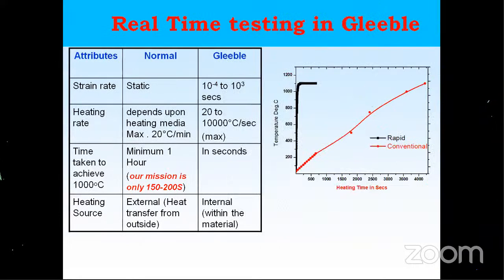Then, this is very, very important. This is, in fact, my own finding, or my own idea actually. Normally, whenever I want to test a high temperature material, imagine I want to test at 1000 degrees centigrade, it takes my machine, a normal UTM, nearly 1 hour to reach the temperature and test. In fact, our mission, whether it's the Vikas engine or the cryogenic engine, I'll take the Vikas engine, it's a radiator cooled engine. The maximum duration is actually 150 to 200 seconds, depending upon the range.